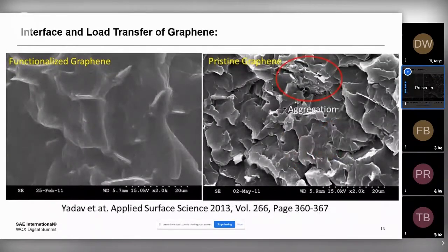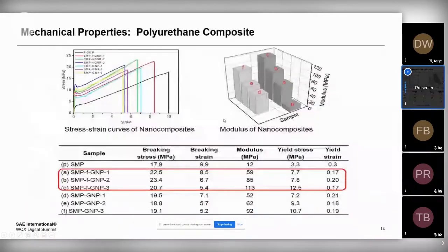Further on, he also shows that depending upon how you do this, you get a very different fracture mode in terms of the material that you produce. If you break the material that has a functionalized graphene and you look at the very edge of it under an SEM micrograph, you still see a smooth edge, and you see the graphene platelets are still immersed in the polymer. Whereas if you're working with an unmodified, untreated graphene, there isn't as strong an interface between the graphene and the polymer. As a result, you get a fracturing where the platelets are broken open and exposed and separated from the polymer. And that's what you see on the right. So there are some examples of things they found that shape our thinking today.